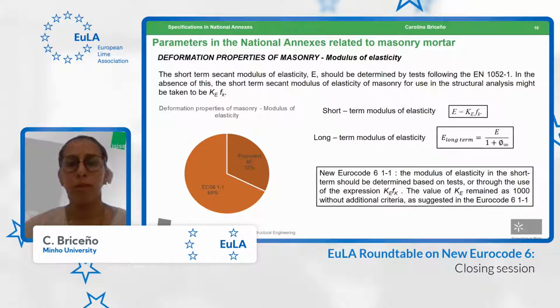There are also parameters related to the deformation properties of masonry, in this case the modulus of elasticity. According to the 1995 and also the 2018 version, the short-term secant modulus of elasticity should be determined based on the tests indicated in the standard 1052 part 1. However, in the absence of this, the short-term secant modulus of elasticity can be taken considering the expression shown here in the slide, where the value of the constant Ke is 1000. This value remains the same for both versions of the standard, and there is no additional criteria to determine this one. It also mentions the long-term modulus of elasticity, which we see is also based on the short-term modulus of elasticity.